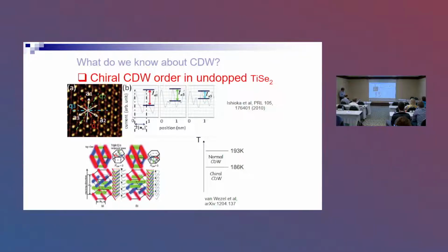The second experiment, also quite interesting, was done with STM, measuring what kind of charge density wave happens near the surface. This group says that STM is sensitive not only to the very last layer, but also the next one and the one after. They found 3 different domains, and in each domain they see a charge density wave in one direction. Altogether, this is a triple-Q charge density wave. To describe it, we need simultaneously 3 vectors at 120 degrees to each other.